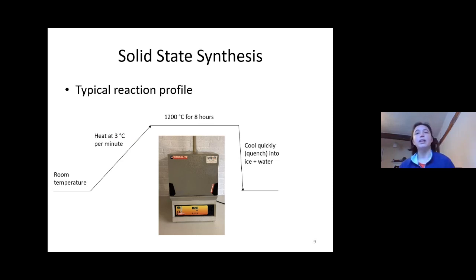And you can see that all of these steps will have different things that we can vary in order to make the reaction better. So the heating rates, the cooling rates, how long it stays at the highest temperature, and what that temperature is. But the key thing is that because it's high temperature synthesis, and because of the way the atomic diffusion rules how the sample is made, we're always going to form the most stable possible product. And the problem in solid state is that if you form a mixture of products, what you've actually got is tiny grains of all those, say, products A, B, and C, and they're all mixed together, and it's not normally very easy to separate them.